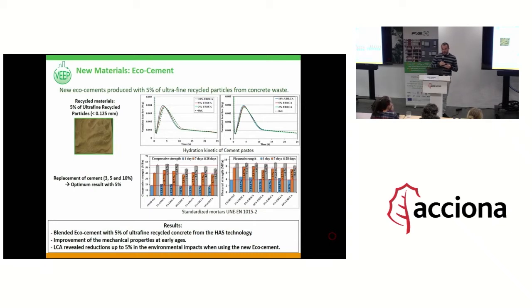In this case, we tried to replace a part of the cement with the ultrafine particles recovered from the HAS technology. We tried to replace directly 3, 5, and 10% with this recovered material, and we tested in cement paste and mortar the hydration of the cement and the compressive, the mechanical behavior of the mortars. We observed that when we replace the cement up to 10%, we accelerate the hydration kinetic of the cement at early age, and we increase the compressive strength of the mortars made with the cement. So answering the statement of Alessio at the beginning of the workshop, I think, yes, we can reduce the environmental impact by replacing part of the cement by new addition coming from waste.